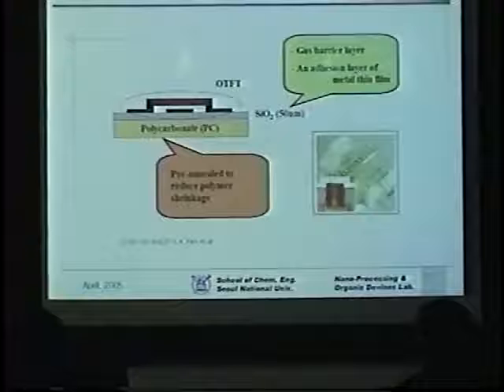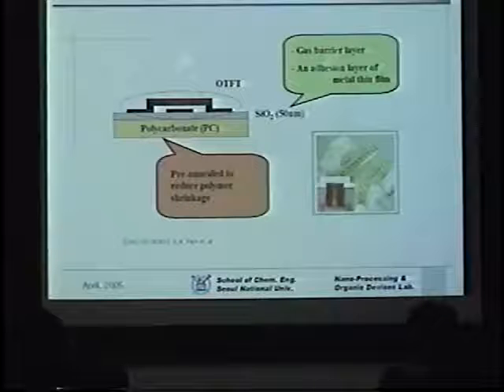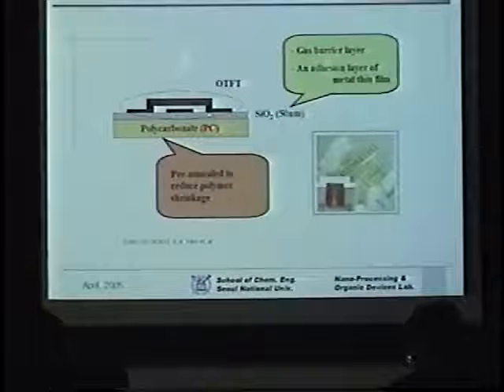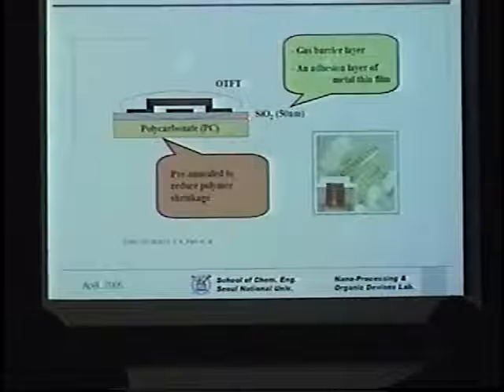The traditional approach for coping with this kind of problem was to use a multi-layer structure. And shown here is one example. We have a silicon dioxide layer on polycarbonate. And in fact, this SiO2 layer is protecting the device from the air and the moisture coming through this polycarbonate substrate.